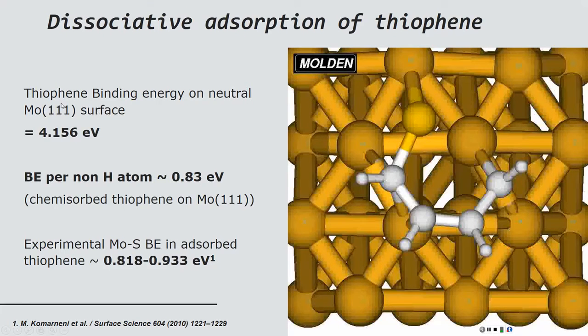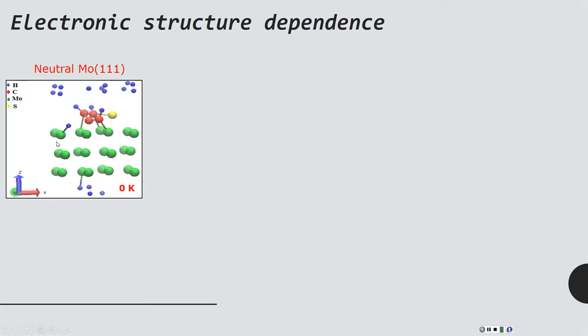Here we also calculated the binding energy of this thiophene molecule on the neutral molybdenum surface, and it is found to be 4.1 electron volts. If we calculate the binding energy per non-hydrogen atom, it is about 0.83 electron volts, and it suggests that this thiophene molecule is strongly chemisorbed on this molybdenum surface after adsorption. And also our calculated results are in qualitative agreement with experimentally determined data. Then we determined the catalytic electronic structure dependence on this thiophene hydrodesulfurization reaction.